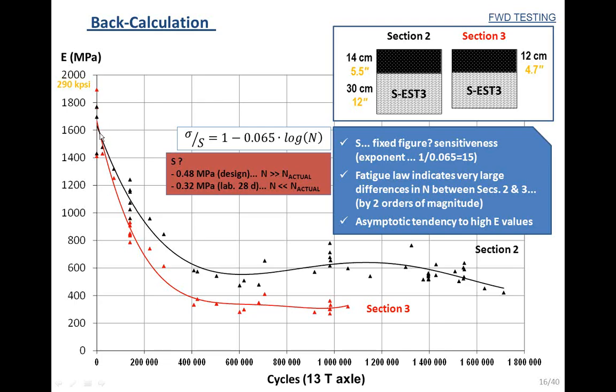When you see section number 2 and section number 3, the first thought is that section number 2 is performing better because the thickness is also higher. You can see here the total thickness of section number 2, and the total thickness of section number 3. So in some ways these differences make sense, but when we were predicting the life of these sections at the beginning of the test, we were applying this formulation, which we have used in Spain for different...